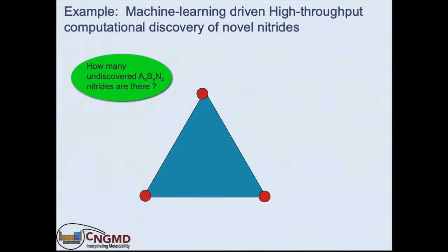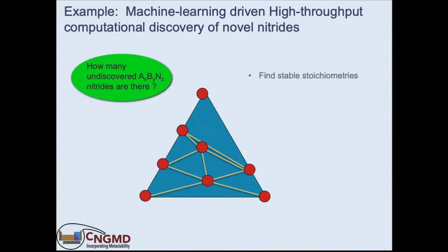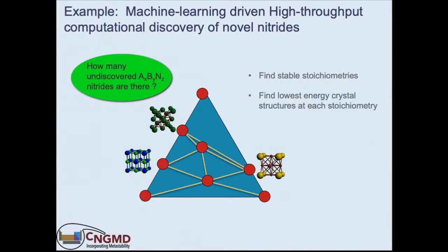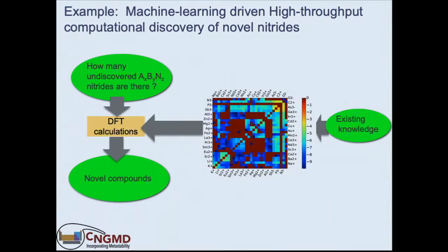So we did binary metal, so ternaries, right? 2 metals, A, B, and nitrogen, and we wanted to see how many new compounds we could find. And so there are 2 problems, right? You first have to find the stable stoichiometries in this ternary phase diagram, and then you have to find what the crystal structure is there. Again, we do that with data mining driven algorithms that drive the density functional theory, right? So the ultimate accuracy is still the one of density functional theory, but the data mining is essentially guiding you to what are the likely stoichiometries and what are the likely crystal structures, and then you calculate their energetics.